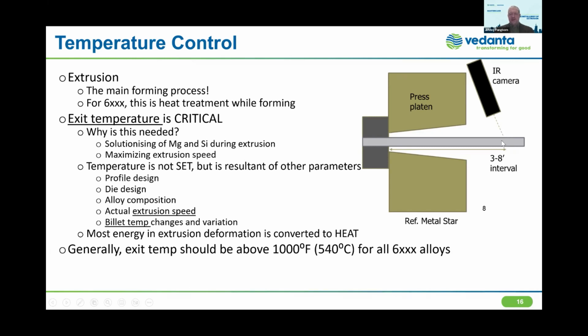But this is a critical control parameter for everyone in the extrusion business, because we are intending to solutionize the magnesium and silicon in extrusion. So we're actually doing a solutionizing heat treatment in this process. And of course, we can use this as feedback for maximizing our extrusion speed while maintaining, or actually very often improving, our quality as we increase speed.